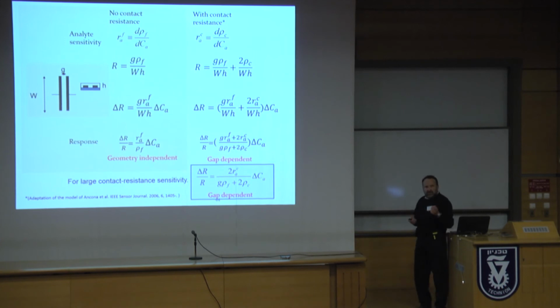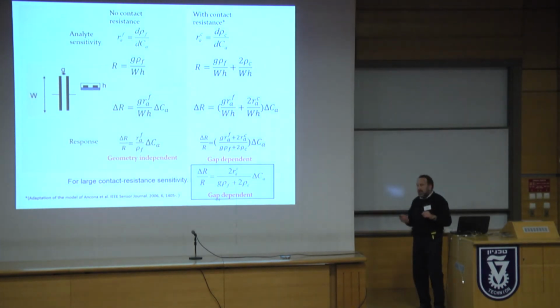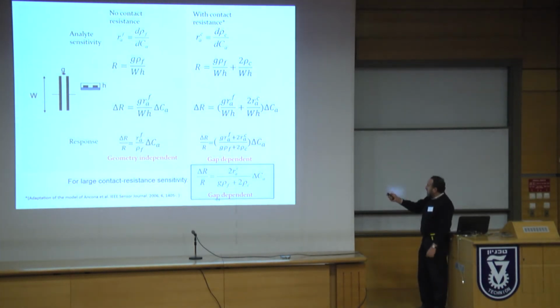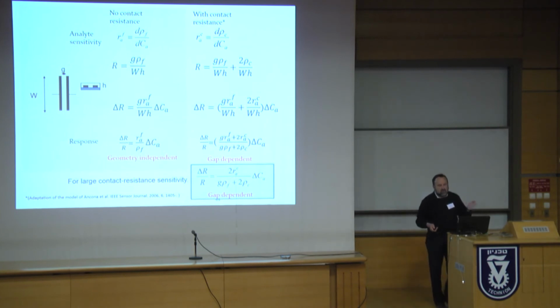However, if you introduce contact resistance, then only then you can see some effect of gap. The gap effect will be larger when there's a large contact resistance sensitivity. Now, we didn't see the sensitivity to toluene, but I believe we saw it towards water. Somehow the contact resistance changes very much when it's exposed to large amounts of water.